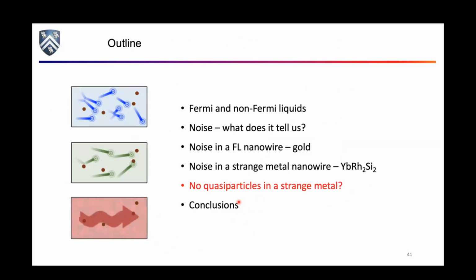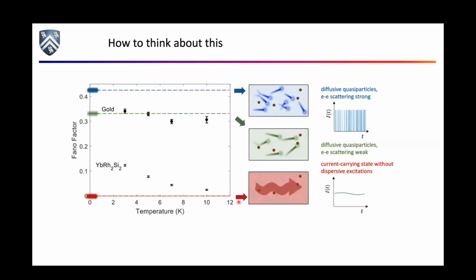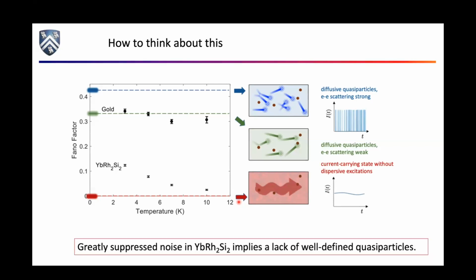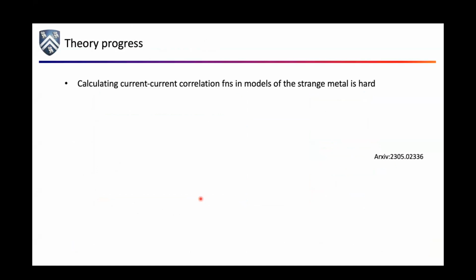So, what does this mean? I think it's tempting to say that this implies the quasi-particle picture, the idea that the current through this device is being delivered by discrete lumps that you can readily identify as propagating quasi-particles, maybe just doesn't work. Maybe the dramatic pronouncements that quasi-particles don't really exist in the system are experimentally consistent with what I'm saying. Now you have to be careful. Having the noise be truly zero would imply that there's no dispersive anything left over that would sharpen up as you cool down.